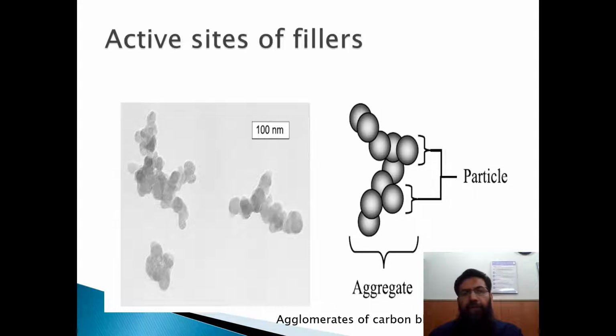Just like for carbon black, you can see here, there are different particles of the carbon black which are linked with each other to make an aggregate, and different aggregates can link with each other to make the agglomerate. And the interaction of one particle with the other particle is due to the presence of different active sites. In carbon black, we can have the hydroxyl group, the carbonyl group, the hydroquinone group, and the presence of different polyaromatic sites on the surface of the carbon. And that is due to the byproducts which are formed during the manufacturing of the carbon black.